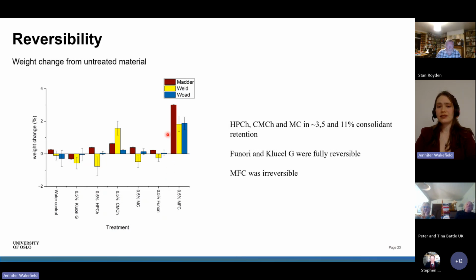The microfibrillated cellulose is not reversible, but I didn't expect it to, because in that case, it's not dissolved in the material. It's particles. So it's no surprise that it then doesn't wash back out. And again, this could be problematic.